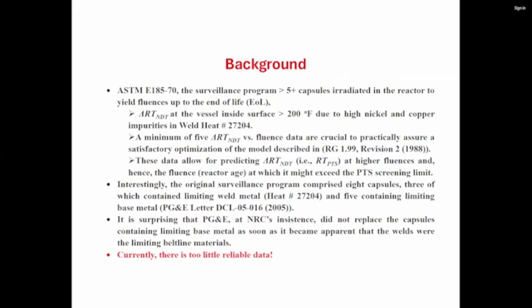Interesting, the original surveillance program comprised 8 capsules, of which 3 had the weld metal 27204 and 5 contained the base metal. And it's surprising that PG&E and NRC did not insist on replacing the base metal capsules with additional capsules containing weld metal, so that we would have a good body of data. The basic problem with Unit 1 is that we have too few data. Next slide.